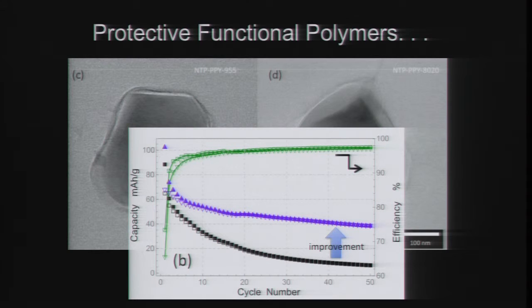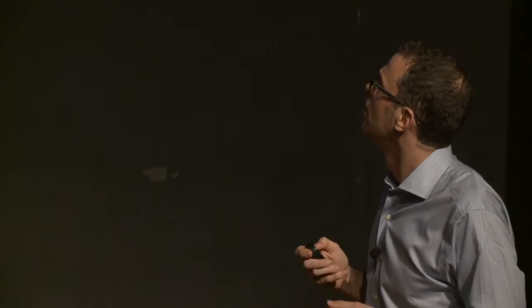Now, this is a very aggressive, high-temperature, sort of dwell at abuse conditions test. So if we don't improve it at all, we lose almost all the capacity in 50 of these test cycles. But we get a substantial improvement if we coat with this material. So just an example of how we look at things to make them better. And again, we're trying to go from days of use, to years of use, to decades, multiple decades of use to justify the expense that's inherent with this kind of technology.